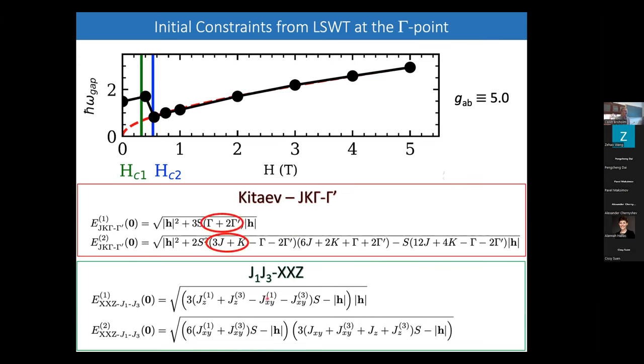And you'll notice that in the expression for the Kitaev model, what shows up is the gamma and gamma 1 parameters. They always appear as gamma plus 2 gamma 1. And J and K, that's the Heisenberg component and the Kitaev component, always show up as 3J plus K. So that becomes kind of the parameters that we can extract from this kind of analysis. Likewise, for the J1, J3, we have the sum of J1 and J3 for the in and out of plane components. Those are the parameters that show up.